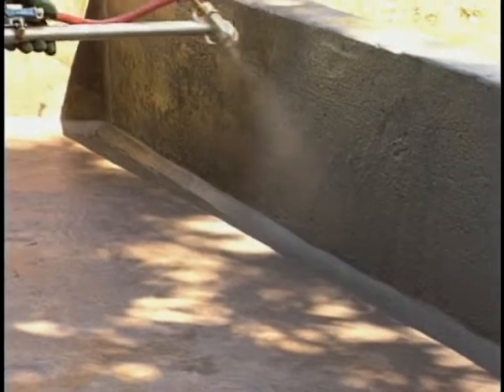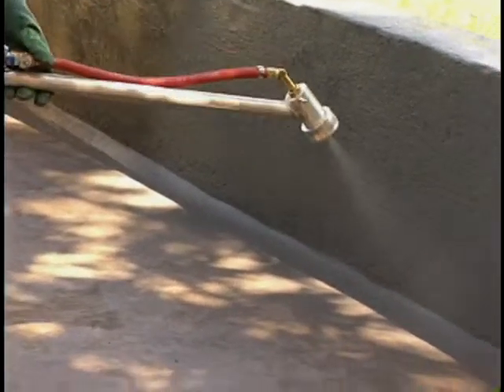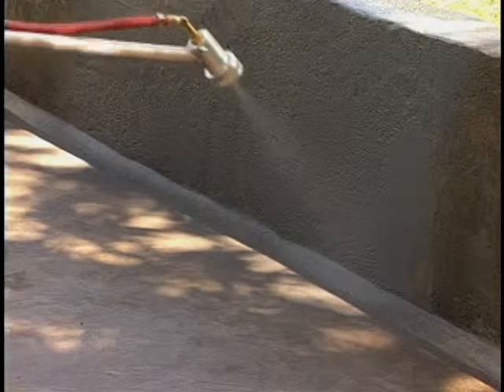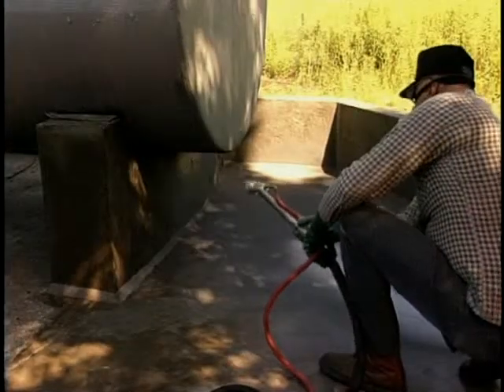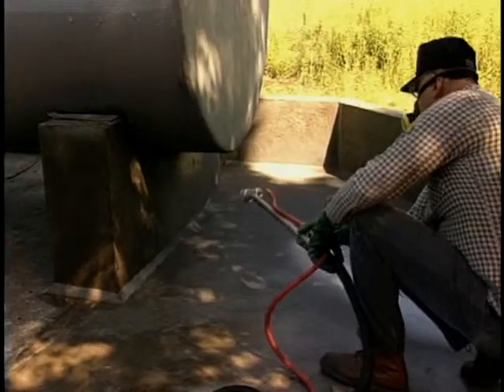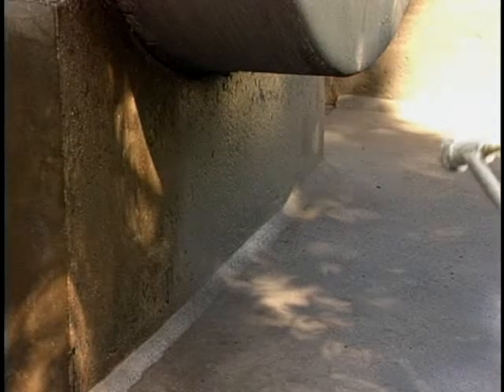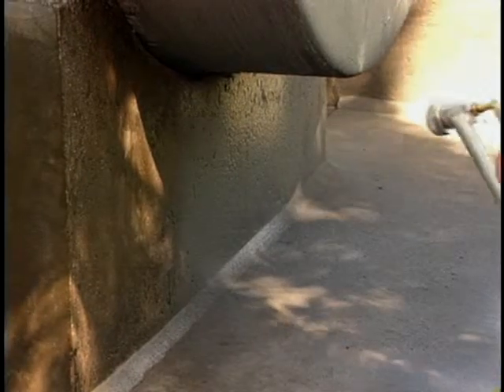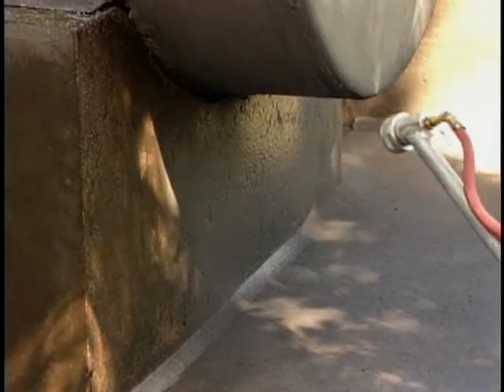Hold the pole gun approximately 2 feet from the surface and slowly move back and forth to attain the desired thickness. 1/8 inch to 3/16 inches for floors, 1/8 inch coatings for walls and ceilings. To attain a 1/8 inch coating on walls and ceilings, 2 1/16 inch coats may be required.